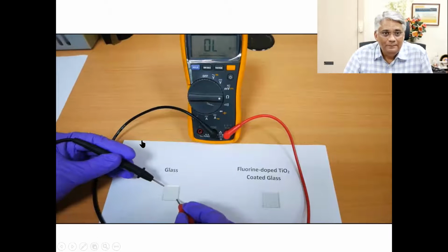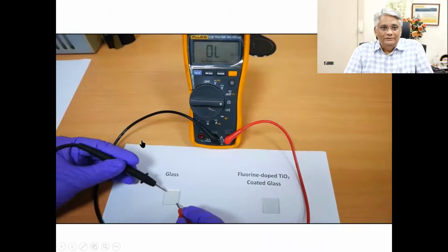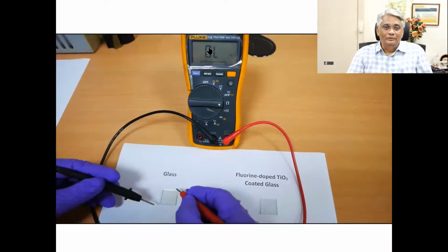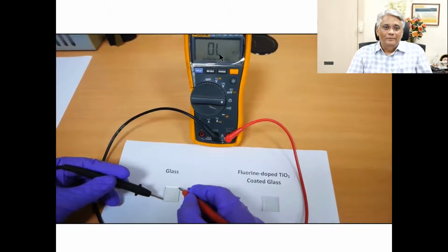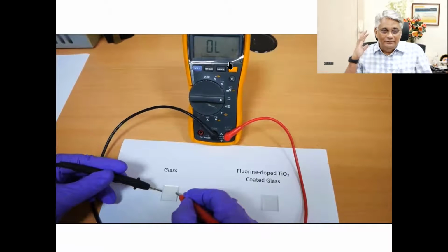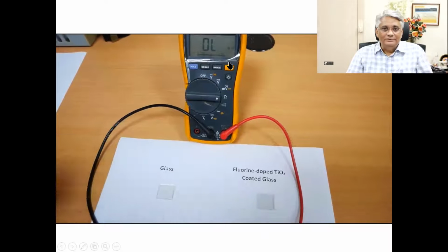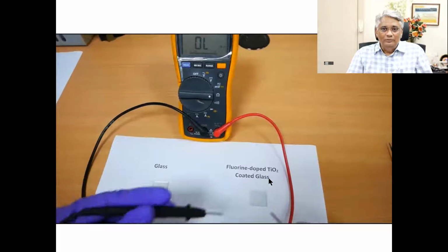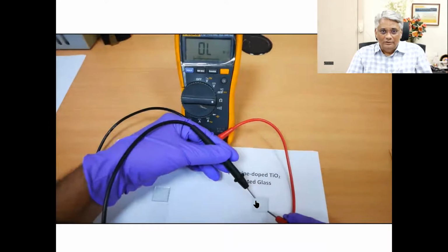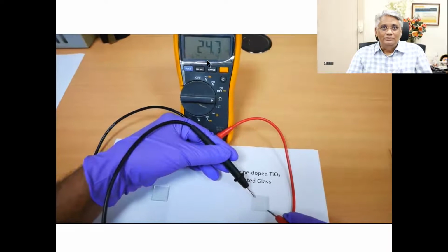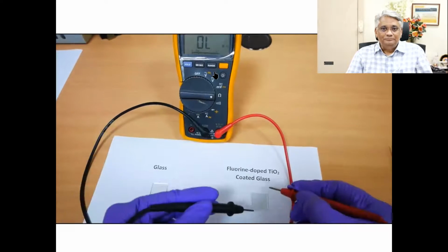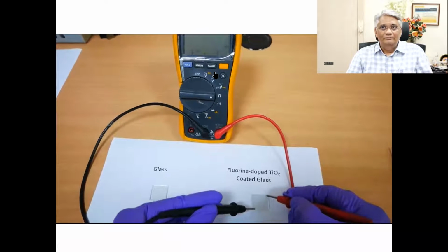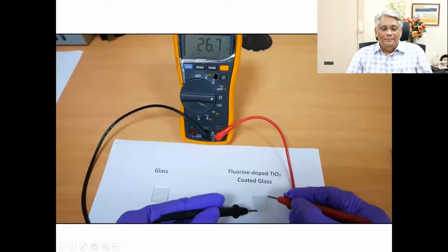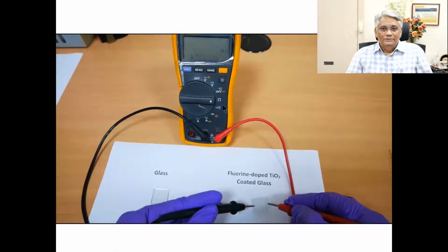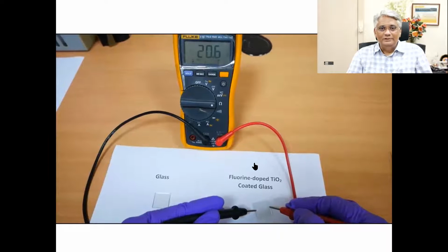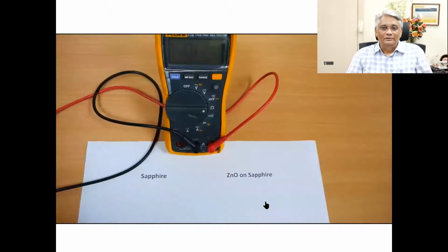I'm playing it again. So we start with showing the glass. You look at the meter up there, overload. That means extremely high resistance. And then you have fluorine-doped titanium dioxide coated on the same glass piece. It shows 24 ohms. Very interesting, is it not? You see that you have transparency as well as conducting nature of the surface.